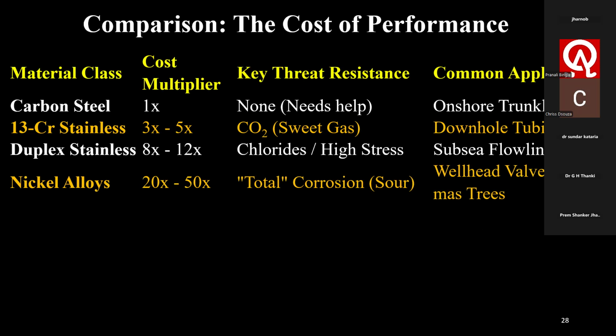13 chromium stainless steel is 3 to 5 times costlier than carbon steel, whereas its key threat is carbon dioxide, sweet gas, and the main application is the downhole tubing. Duplex stainless steel is 8 to 12 times costlier than carbon steel. Its threat is chloride and high stress, which it will resist much better, and a common application is the subsea flow line.